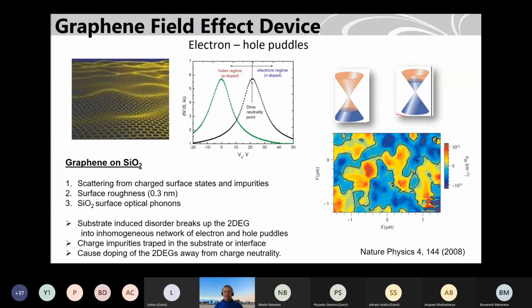So how to get very high quality graphene? That is also quite challenging. And from 2008 onwards, people already know that graphene is not very perfect. What you see, graphene on silicon oxide, it has lots of disorder. And people have measured with Kelvin probe microscope that some parts of the graphene are p-type and some parts are n-type, as you see here. So this is n-type, this is p-type graphene Dirac bands.